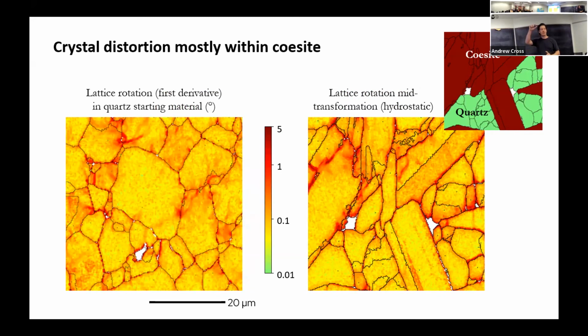we're not actively deforming the sample here, we're just taking it across the phase transition. We've got a big region of coesite in the top left here, and then a few quartz grains down here, in here, and in here. So the quartz in this case, if we just think about that, this is possibly even less deformed than it was to begin with. And all that comes from is the fact that this one was sat around under hydrostatic conditions for a bit longer at temperature, and so you've annealed out and you've gotten rid of some of the defects that were in the starting material.